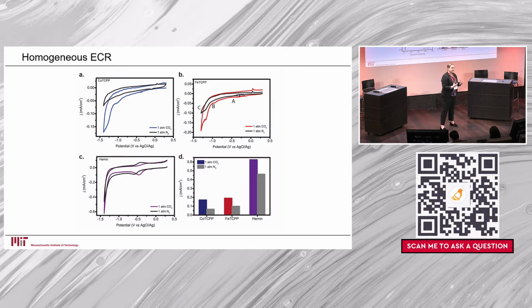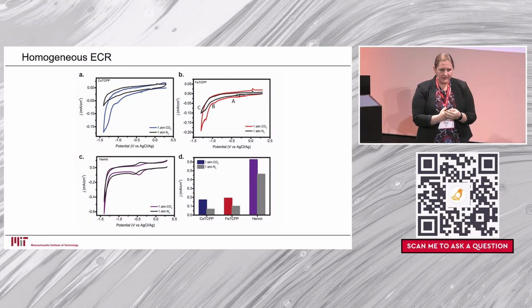And so we started by just looking at catalysis with these small molecules. And so what you'll see here in each of these is just the amount of current generated, which indicates how much we're transforming whatever's in the system, in either nitrogen in the black or in the color in the second graphs. And so if you look to the left of each of the graphs, you'll see that the peak is significantly lower for the colored one. That indicates catalysis is occurring, which is fantastic.